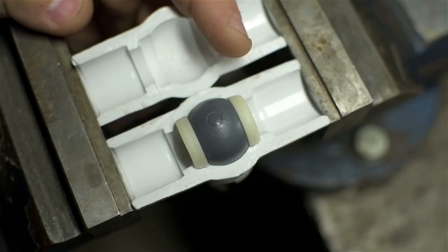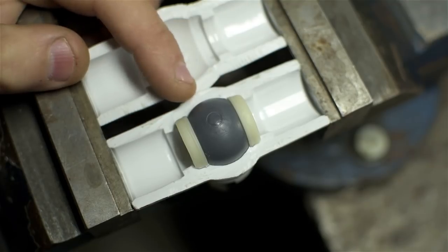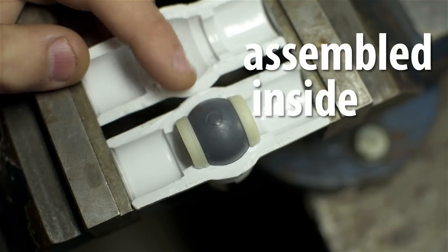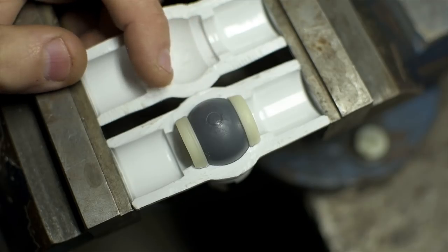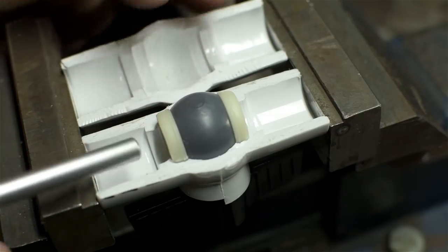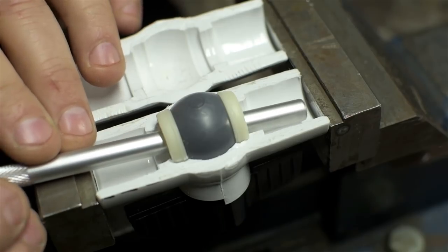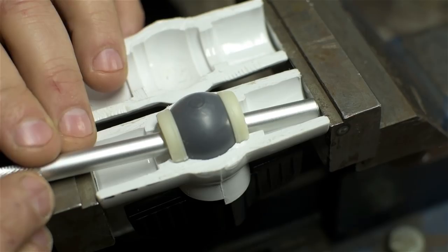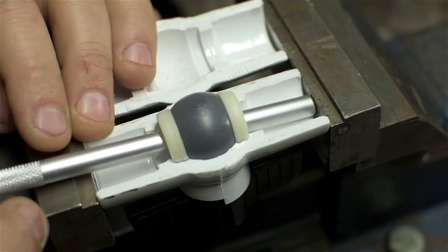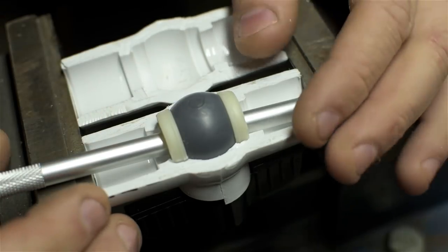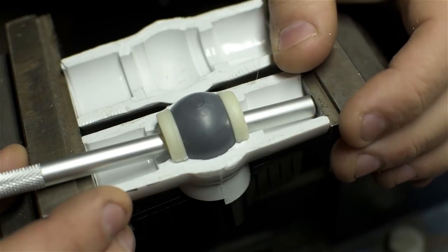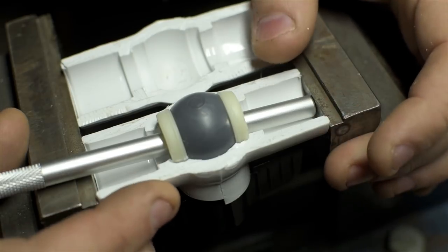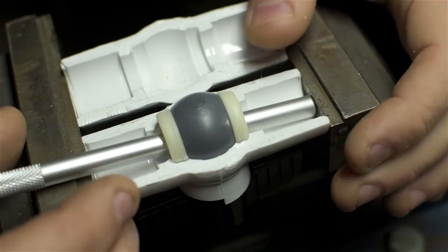The ball in this ball valve, along with those seals, were assembled inside the mold. Let that just sink in a minute. Assembled inside the mold. Just saying that out loud is giving me goosebumps. Now this next part is speculation because I wasn't inside of the mold when this happened, but I'm pretty sure the ball and seals were assembled onto a mandrel in the injection molding tool, probably by a robot and likely on a better fitting mandrel than I'm currently demonstrating. The mold then closed around the ball, seals, and mandrel, just like we saw earlier, kind of coming in along the axis of this valve, and the PVC was injected to create the valve body. It created the valve body around the parts and the geometry that was inside of the mold. Genius.